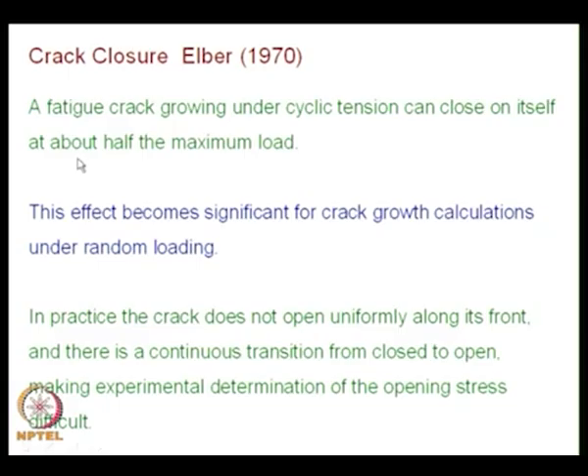And what we find is the crack closes at about half the maximum load. And how does the crack open? What is the difficulty in the experimentation? In practice, the crack does not open uniformly along its front, and there is a continuous transition from closed to open, making experimental determination of the opening stress difficult. See, unless you make certain observations by experiment and then identify these aspects to be modeled by a numerical model, you cannot develop a numerical model. So, initially you need to have experimental observation for such complex phenomena.